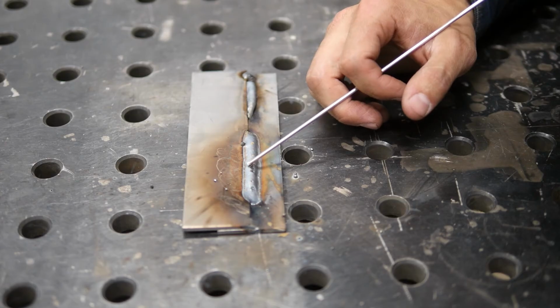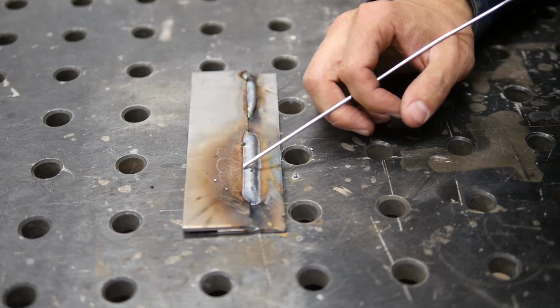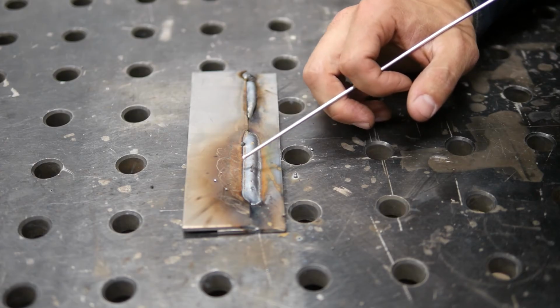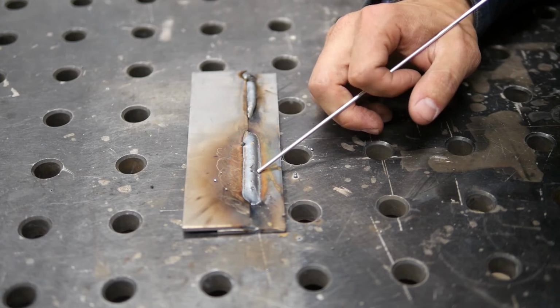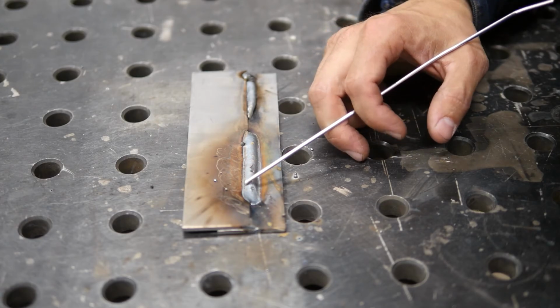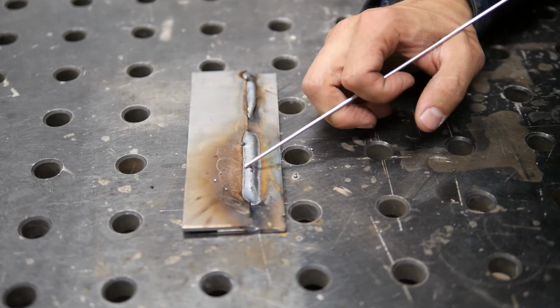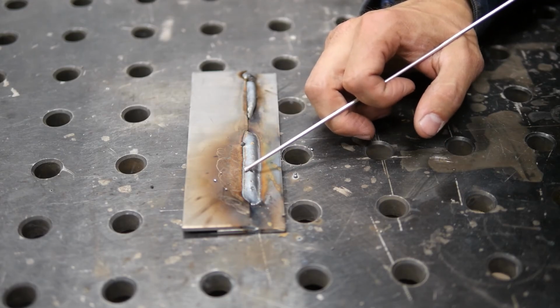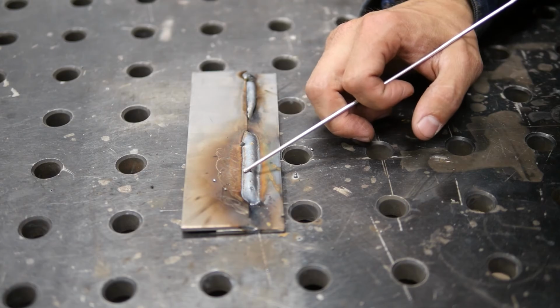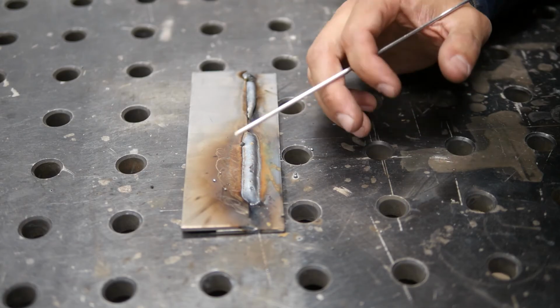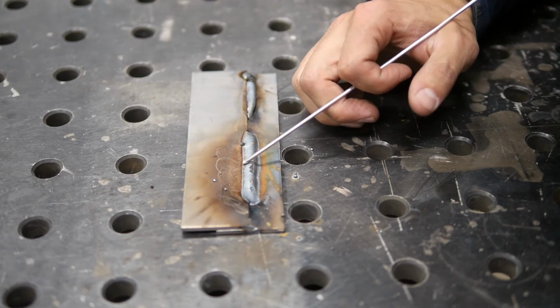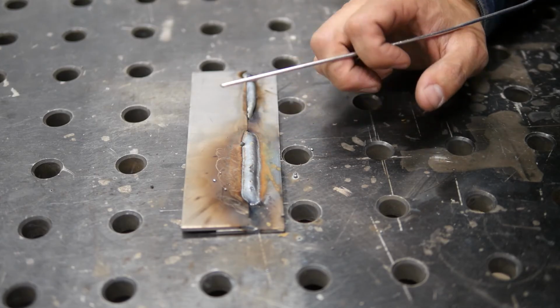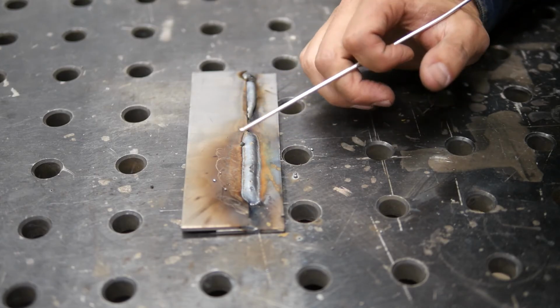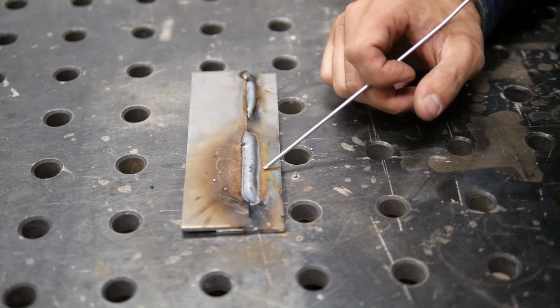The other problem with our voltage being too high is sometimes the arc path or the width of the arc is wider than what the wire can actually fill in, and we tend to get undercut, especially on the upper toe here in this region. And you can tell that by taking a little scraper and going back and forth. If it's not smooth, like there's a little valley there, that's a place where you could have a stress riser and a premature failure.